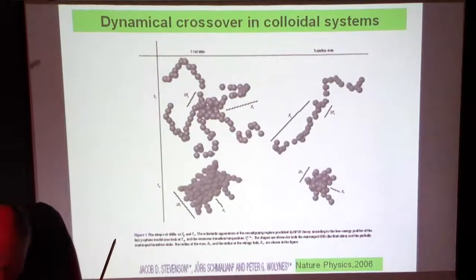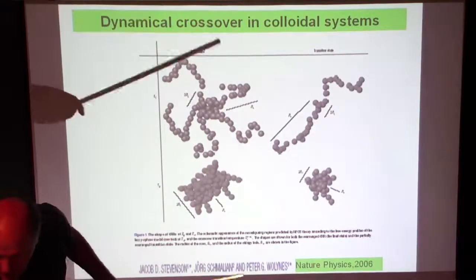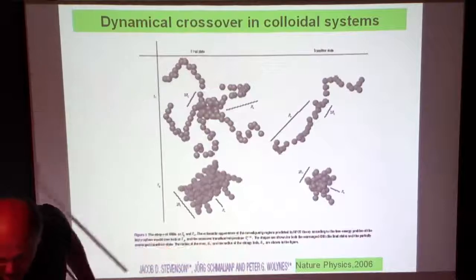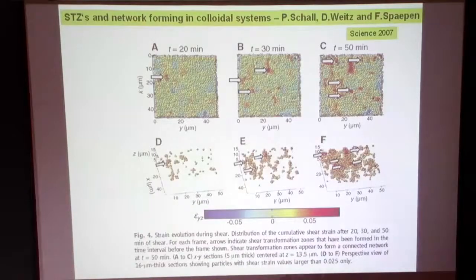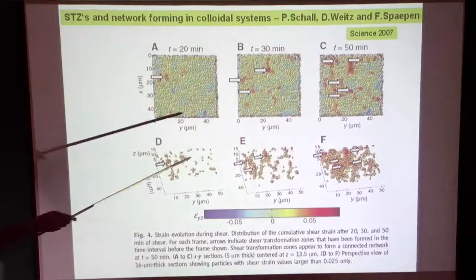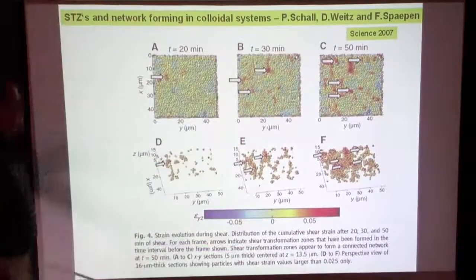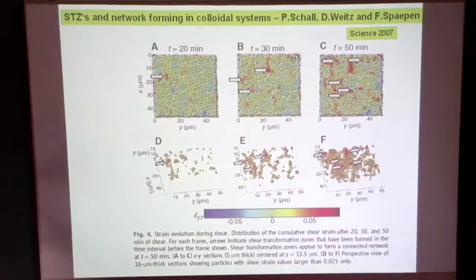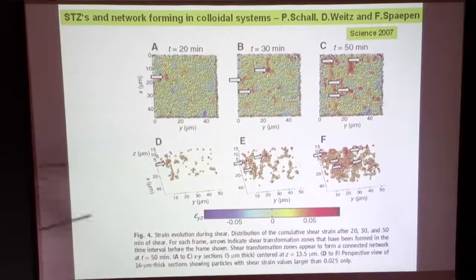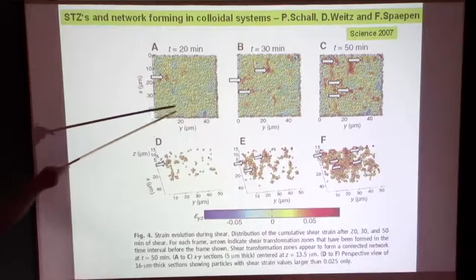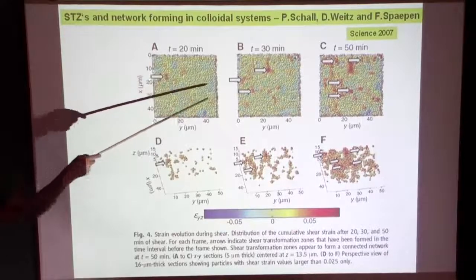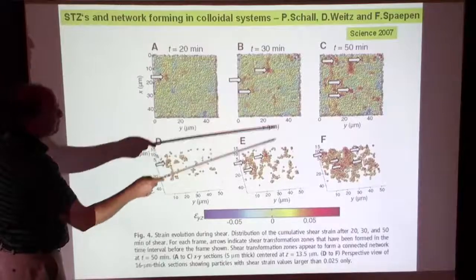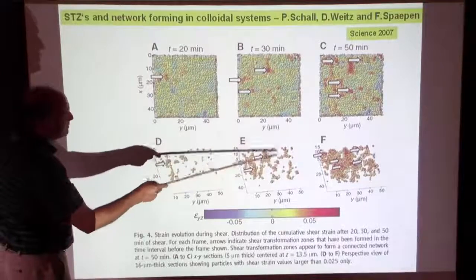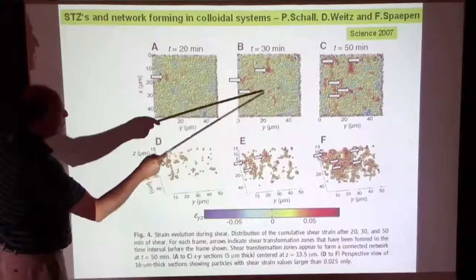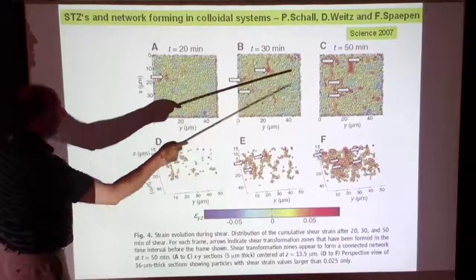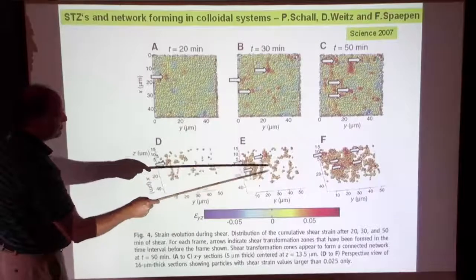But let's go on for a moment and keep it in mind, because right now I'm talking about potential energy only and certain configurations which show up. And these configurations, and this was mentioned during the conference already, is this work from the Weitz and Spaepen group in 2007. They showed when you shear a colloidal system, we have certain hotspots over there where the activity, the motion is very large, these red points, and then there are certain strings in between also. Here, taking out all the other atoms which are blue, which are not moving much under these circumstances. And then you get certain correlations.